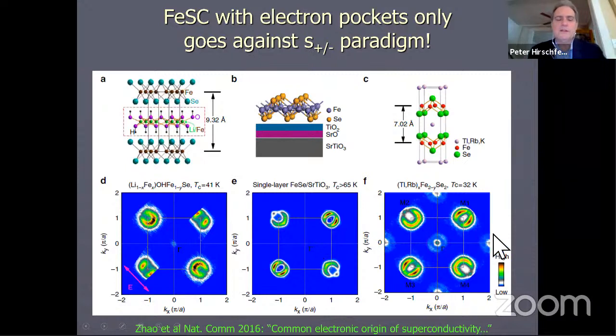In the row below, you see the angle-resolved photoemission images of the experimental Fermi surfaces of these materials. And what you see generally is that the hole pocket is missing. It turns out that the hole band has been pushed down below the Fermi surface. In this last picture, that's not obvious, but this is apparently just a spectrally broad band, and so it has a little overlap at the Fermi surface, but the centroid of the band passes below. So you can ask the question, what happened to the mechanism you told us about, where I should have a strong scattering between the hole pocket at gamma and the electron pockets at M? How can that happen if there's nothing at the Fermi surface at the gamma point?